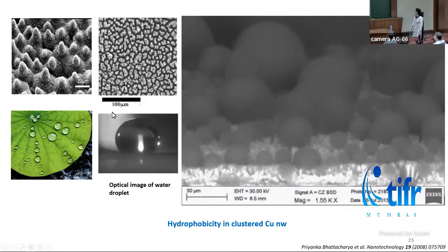But here, if you look at the droplet size, it is very big. So when we image this sample in ESEM mode, we can see that droplets as small as 3 microns to 4 microns are also standing on the sample. That means this sample is truly hydrophobic in nature.